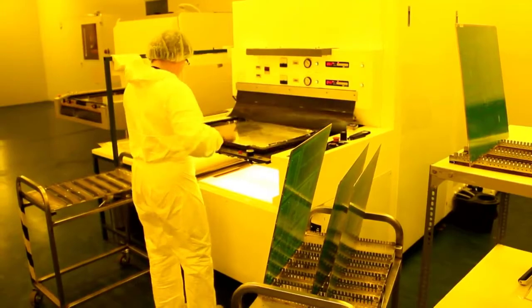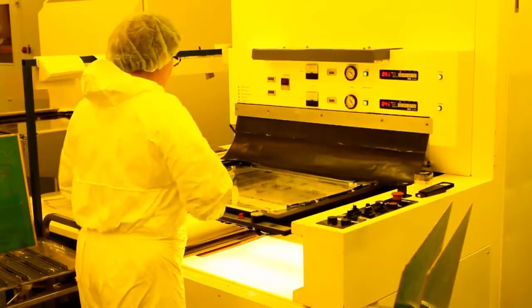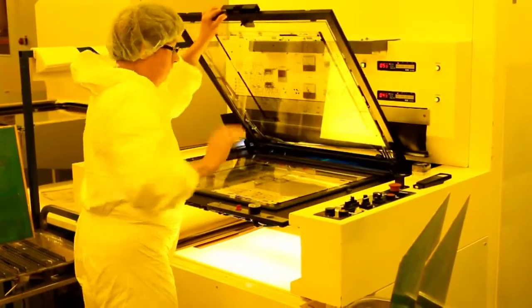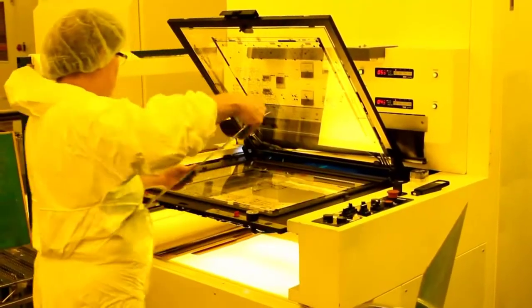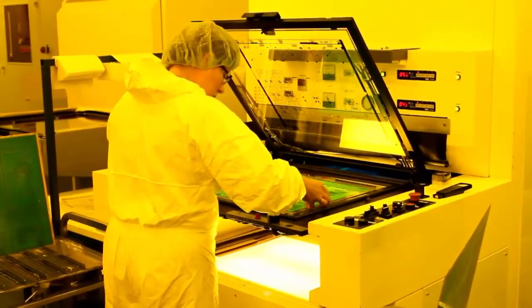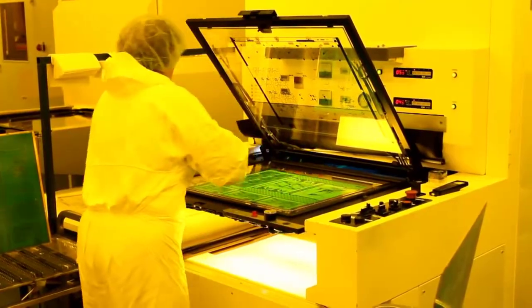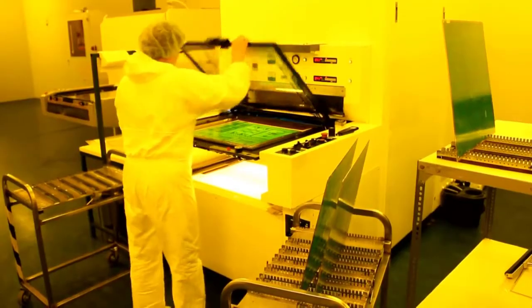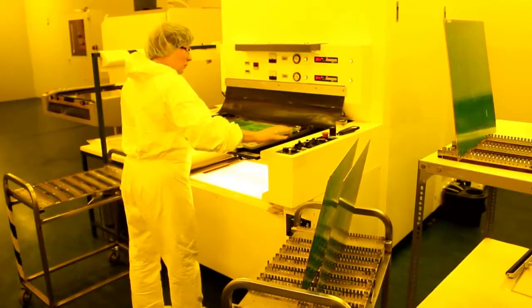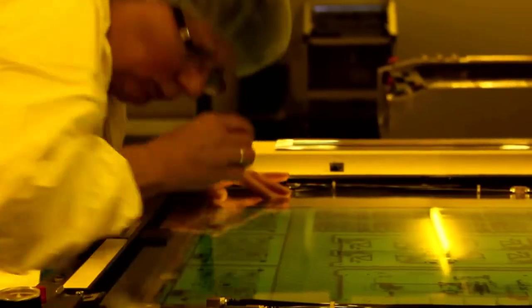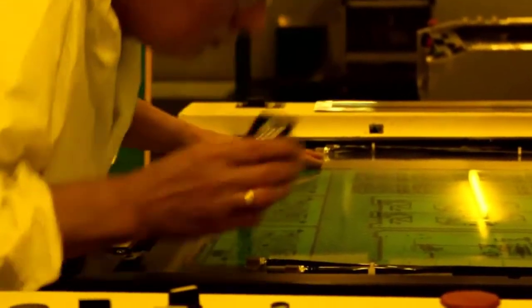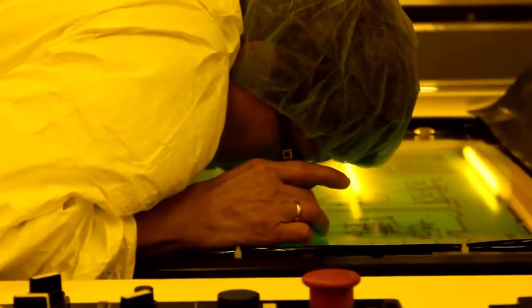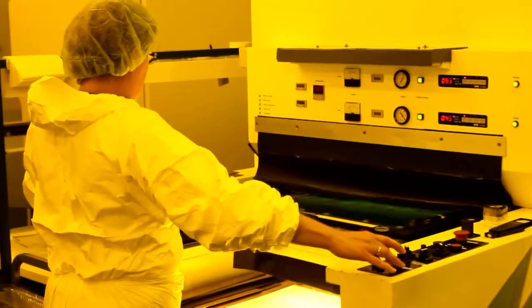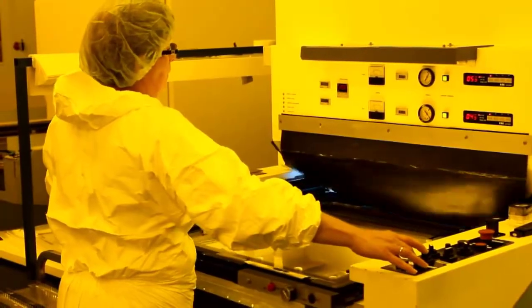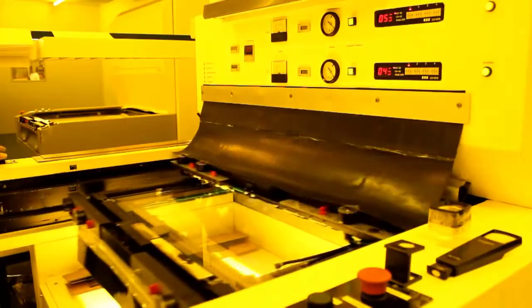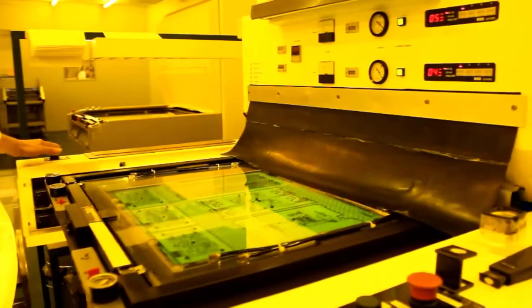Next, the coated panels are imaged. For this, we use a 2-drawer UV printer. The operator mounts the photo tool films on the machine and then places the panel onto the registration pins. She checks that the film and the copper layer are precisely aligned. Mask alignment will be better than 50 microns. As with the etch and the plating resists used earlier in the process, the UV lamps in the machine harden the ink where the film is clear. That is where we need solder mask on the finished board.